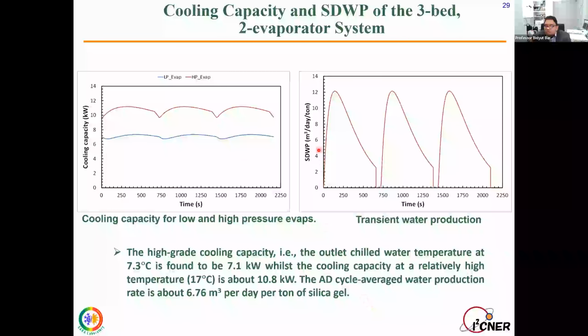So if we have 1 ton of silica gel in our bed, the system will produce 6.76 cubic meters of water in a day if it is continuously operating. Another thing I did not show here: if we don't need this cooling energy for room cooling or process cooling, we can use it to cool down our beds so that our specific daily production can be improved from 6.76 meter cube to 12 meter cube per day. 12 tons of water we can get from this system.